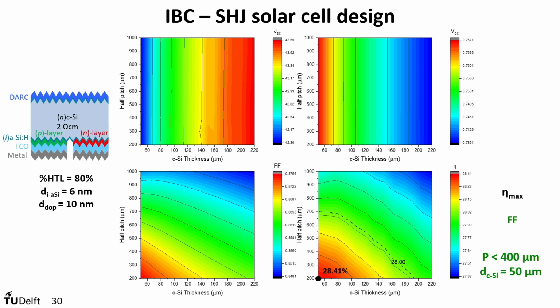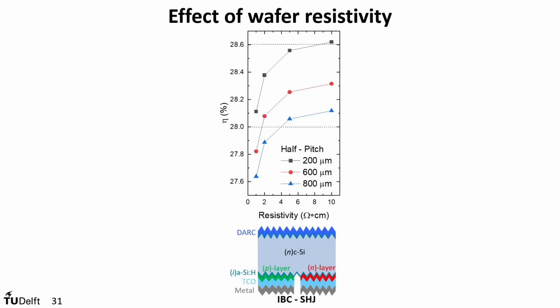So this is what we have found so far, and it can go as thin as possible and as fine as possible, but then of course you hit the barrier of technological implementation. So this is something that we still think is more or less feasible at relatively normal costs, but of course going anything further will only prove to be more or less just an experiment. It's not going to change much. Also in this case we did the effect of wafer resistivity, and if you go for very narrow lines that possibly you can only make at one point feasibly with lithography, still it is possible to push up the efficiency.